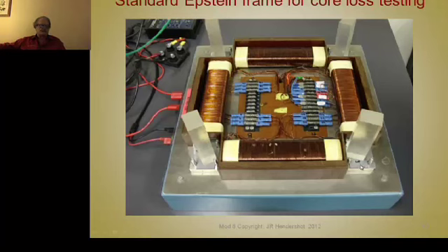So you make these samples with these holes punched in them, and you lay one down, then one across it, then one across that, and you keep doing that, and I don't know how many they put. I think there's 5 samples of each one in each one of these to make this rectangular core. Then you put a little weight on this to get them all to touch, and so you've got an iron circuit there, and what you do is you apply